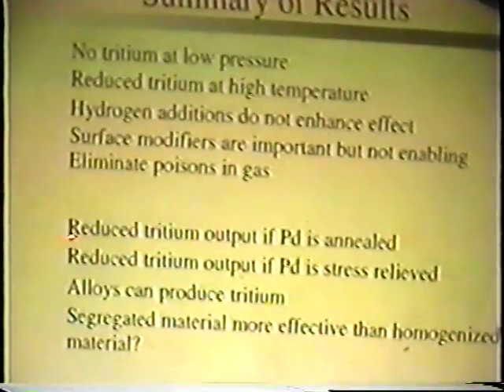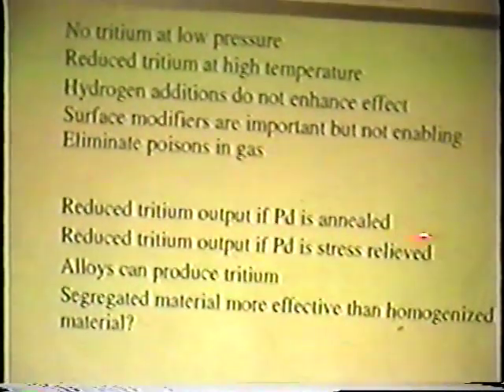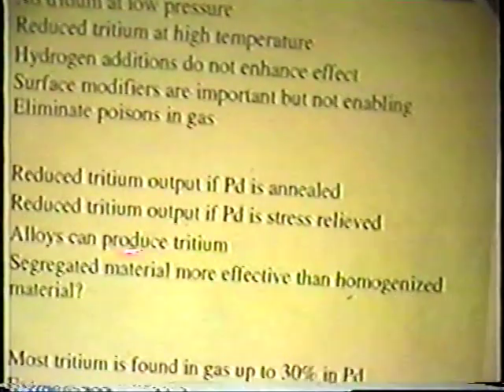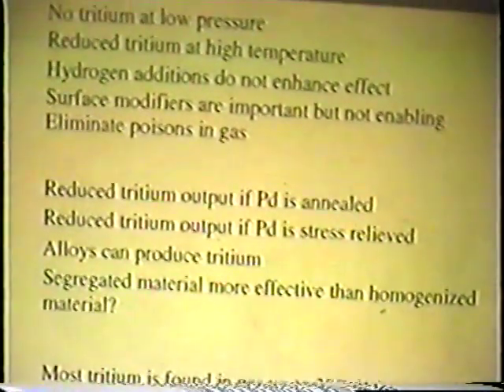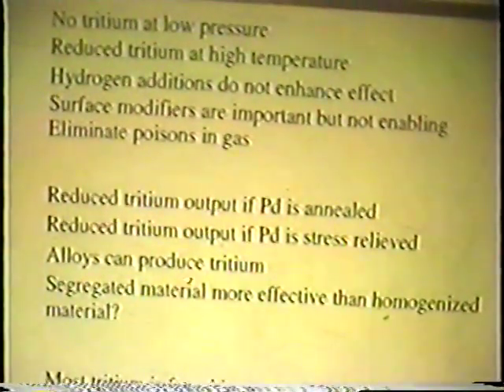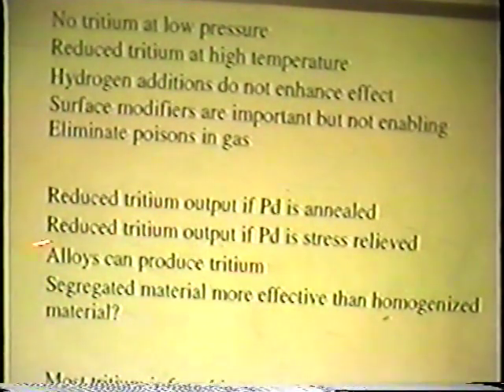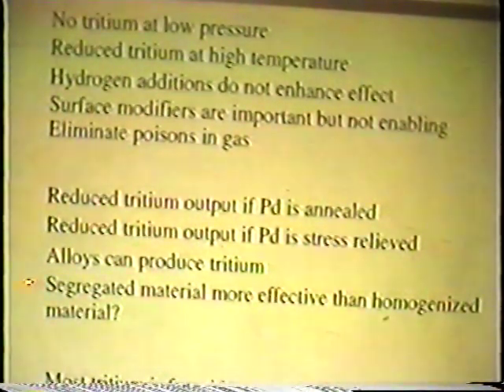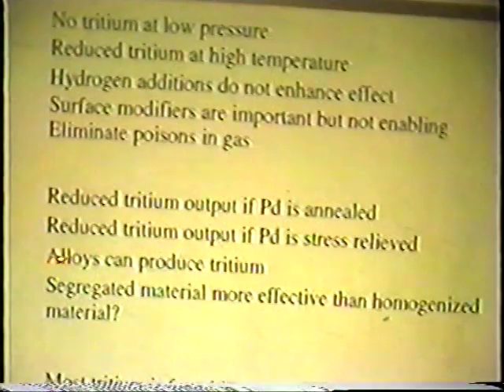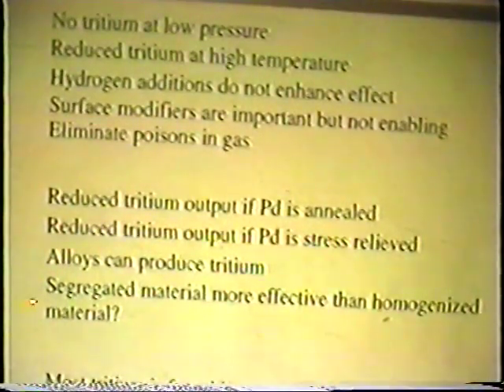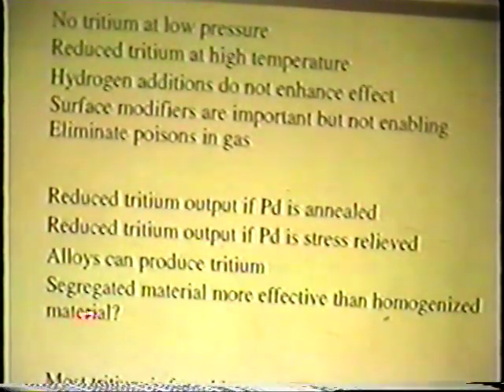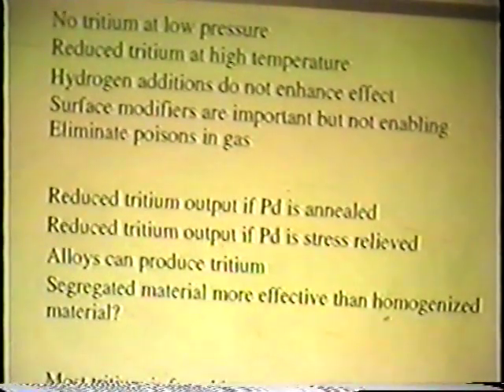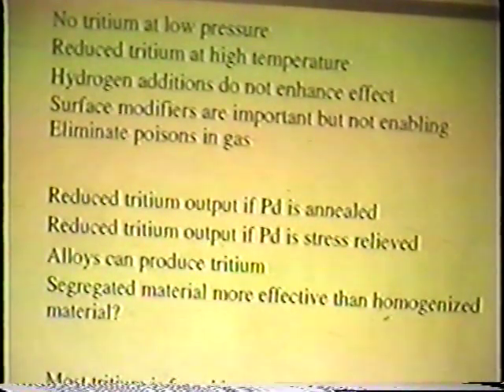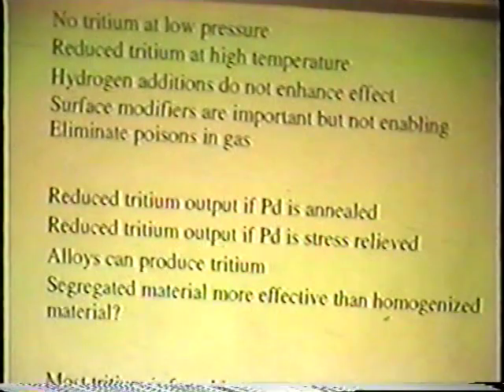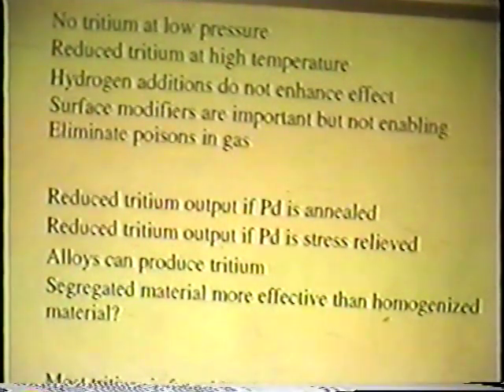We've seen a reduction in tritium output if the palladium is annealed or stress relieved, so we want a stressed sample. These alloys can produce tritium, and that's kind of counterintuitive to what we first were thinking, in that we only got tritium out of the pure materials. Is this segregated material more effective than homogenized material? Well, we have 3 batches. 2 are segregated, 1 is homogenized. The one that's homogenized doesn't do anything, the other 2 do.